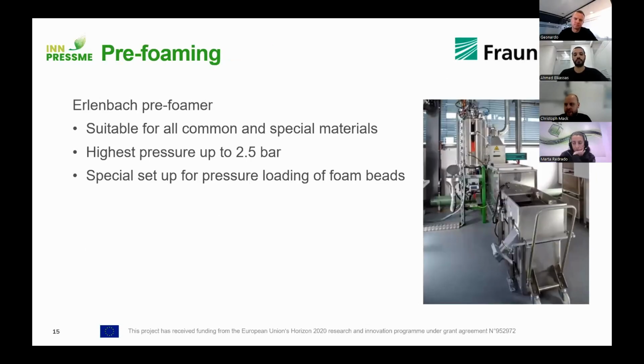in our lab, with our pre-foaming unit, which is a small industrial scale pre-foamer, suitable for all common and special materials. The highest pressure is up to 2.5 bars. And we also have a special setup for the pressure loading of the foam beads.